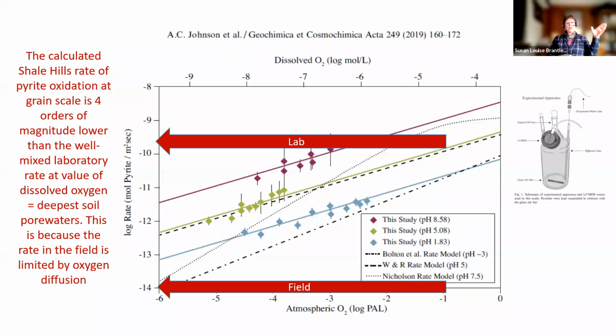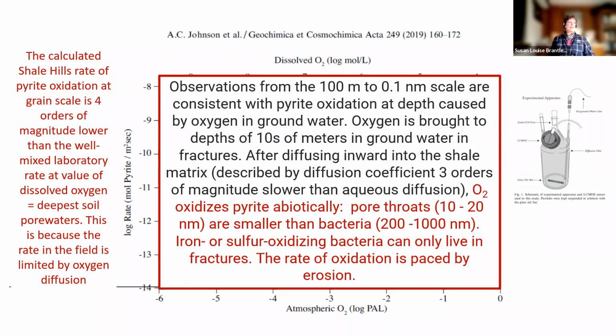So what I tried to show here is that no matter what scale you look at this, you can make a model that shows how this system is working and how this oxidation is happening. So the observations are going from like 100 meter scale to 0.1 nanometer, and they are consistent, at least in this sort of numerical and thought experiment way of thinking about the system. We think that oxygen's brought to the depths of tens of meters in the groundwater to the fracture. It diffuses inward with a diffusivity which is like 3 orders of magnitude slower than aqueous diffusion. And we think it oxidizes abiotically.